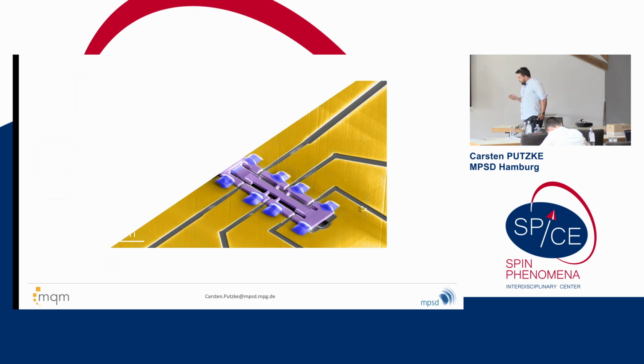Okay, so if we start out with one of those materials or structures, what they look like in our case is that we build things on a substrate, in this case sapphire. We interface our material with that because we don't want to grow or make large structures from the material itself. But we use gold deposition on a substrate to contact our material. And then we build this six-point structure here where we can pass current down the middle and measure voltage, similar to what we've seen before.